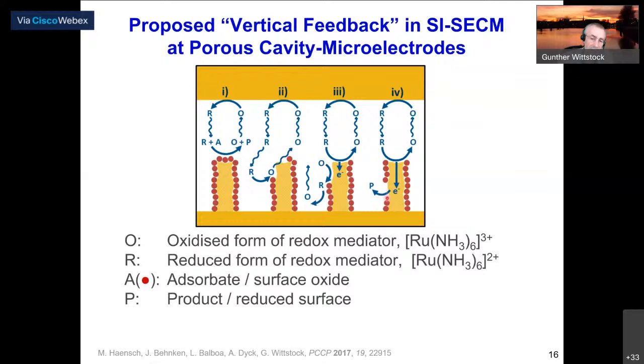And the oxides are also reduced in deeper layers, more or less at the same time as the reduction happens at the outer surface. Due to this connective network, this surface oxide reduction happens more or less all the time and does not necessarily require the direct interaction with these molecules. So both mechanisms are probably present at the same time. And that helps to give a uniform response.